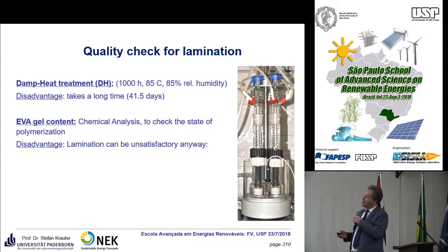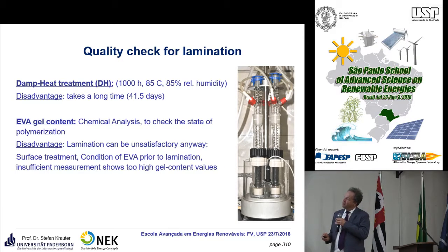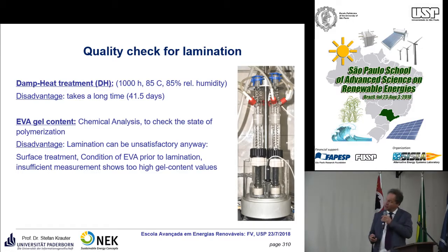But the problem is that even if the lamination is carried out, we can check this and say it's totally polymerized, but if the surface is not correct or the EVA has been polymerized before the actual lamination process, your module will not be able to withstand for a long time. So this is also a big problem.